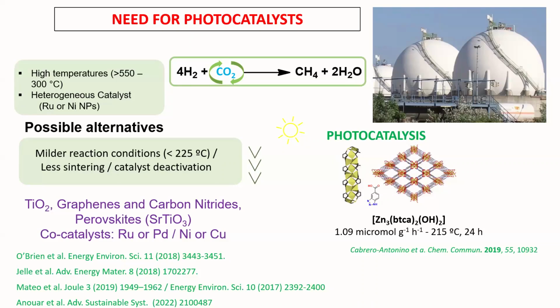When we started this project in 2019, the first example we reported was a zinc-based MOF. The activity was only 1.09 micromole per gram per hour at 215 degrees centigrade after 24 hours. This was the first example of CO2 photomethanation, and we were not very impressed with these results because the activity was almost nothing. But we wanted to develop further, because people say that zinc-based MOFs are not good even for catalysis, because first of all there is an issue of stability, and second, zinc is not very stable.